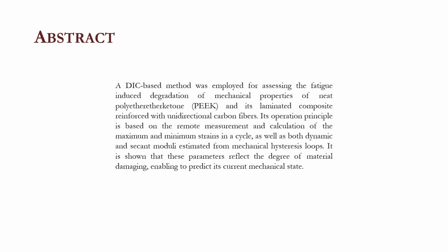Its operation principle is based on the remote measurement and calculation of the maximum and minimum strains in a cycle, as well as both dynamic and secant moduli estimated from mechanical hysteresis loops. It is shown that these parameters reflect the degree of material damage, enabling prediction of its current mechanical state.